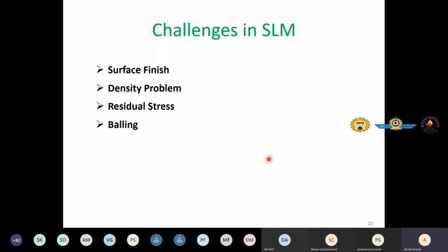So now coming down to challenges in the SLM process, surface finish is one of the prominent challenges because you cannot achieve surface finish better than the particle size. So typically particle size used is 15 to 40 micron. So your Ra value of surface roughness would lie in that range only. But there are many subtractive or micro machining processes where you can achieve very fine surface finish. So this is one challenge. We have to compromise with surface finish.